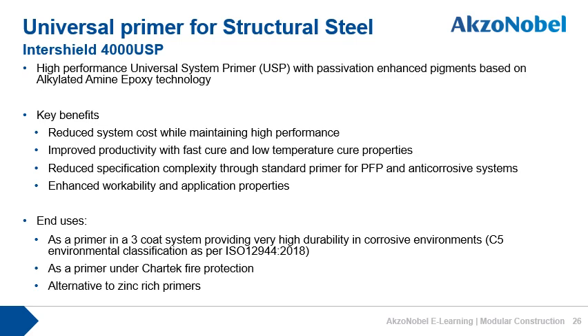Our final pillar of universal protection is the universal primer for structural steel. We have recently launched the Intershield 4000 USP, which is our universal system primer based on alkylated amine epoxy resin technology, reinforced with passivation pigments. This is a breakthrough innovation through which we are now able to replace traditional zinc-rich primers for structural steel without compromising on durability. This leads to significant cost and time savings because Intershield 4000 USP is significantly faster curing than zinc-rich primers, and it can also be applied down to -5°C.